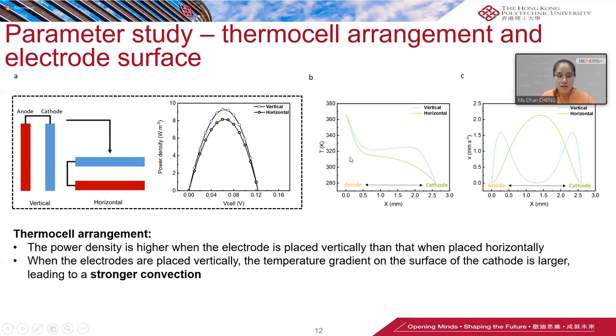So from figures B and C, it can also be seen that when the electrodes are placed vertically, the temperature gradient becomes larger than when the cell is arranged horizontally. And so when the cells are placed vertically, the temperature gradient on the surface of the cathode is larger. That will lead to a stronger convection. As we talked about before, the thermal cell is limited by the electrode kinetics of the cathode. So vertical placement is indeed better than horizontal placement.